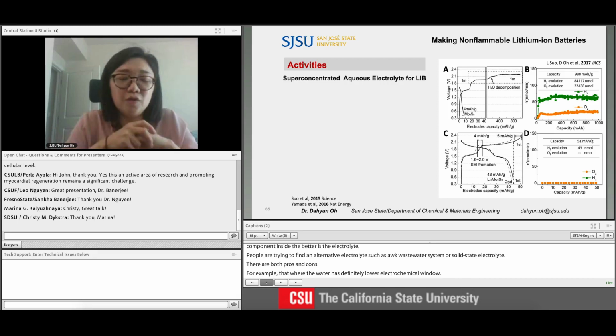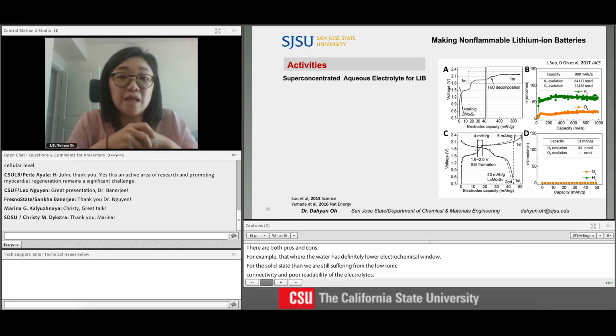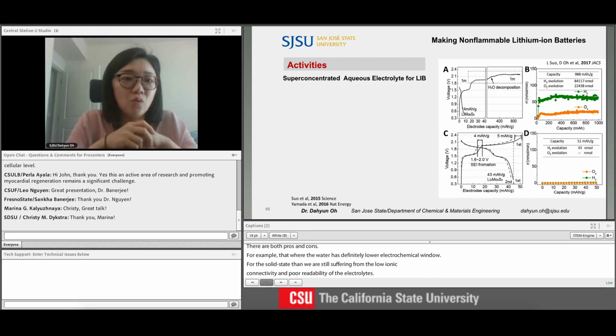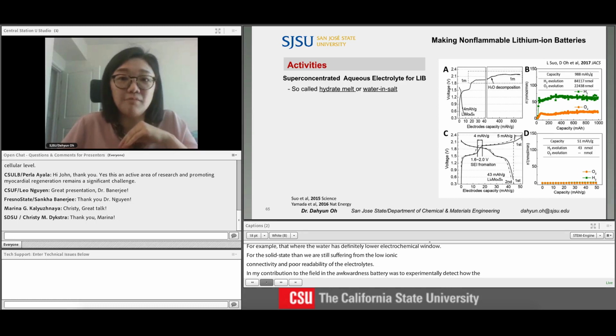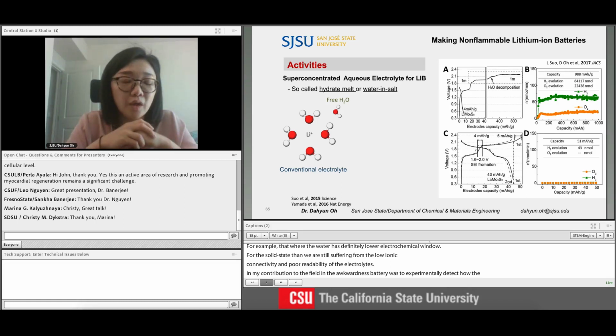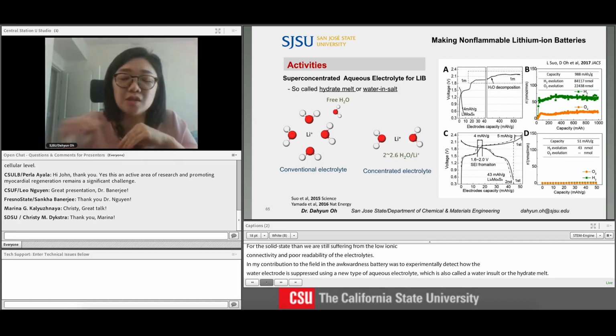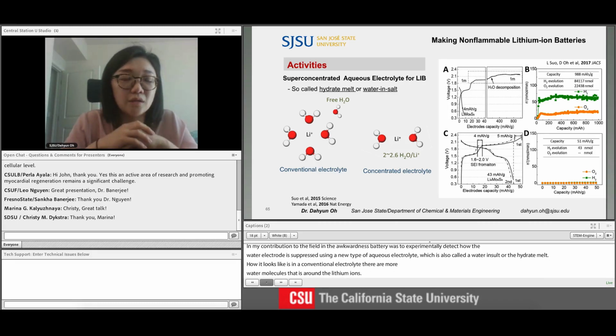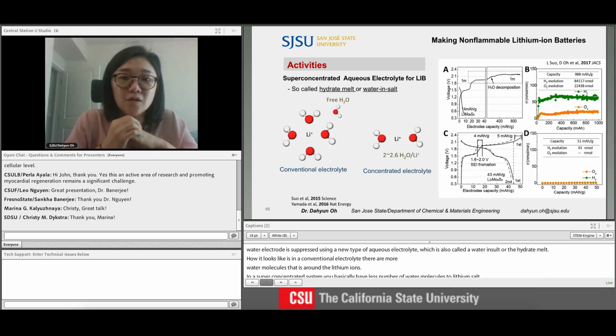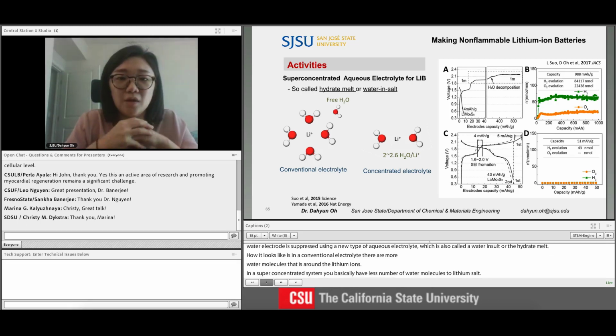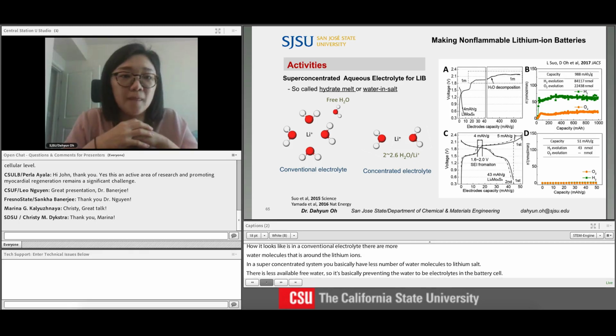My contribution to the field in aqueous batteries was to experimentally detect how water electrolysis is suppressed using a new type of aqueous electrolyte, which is also called water-in-salt or the hydrate melt. In a conventional electrolyte, there are more water molecules surrounding the lithium ions, but in a super concentrated system, you have fewer water molecules bound to the lithium salt. And there is less available free water, so it basically prevents the water from being electrolyzed in the battery cell.